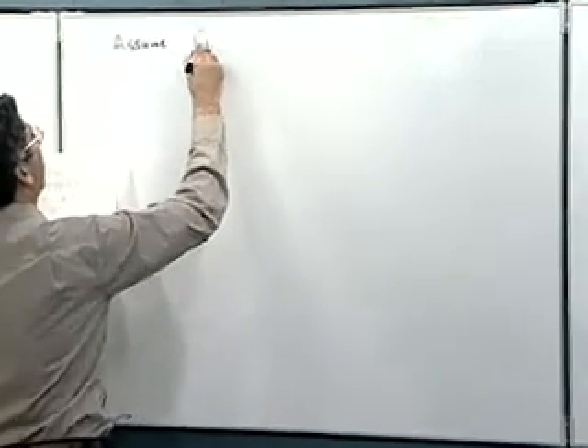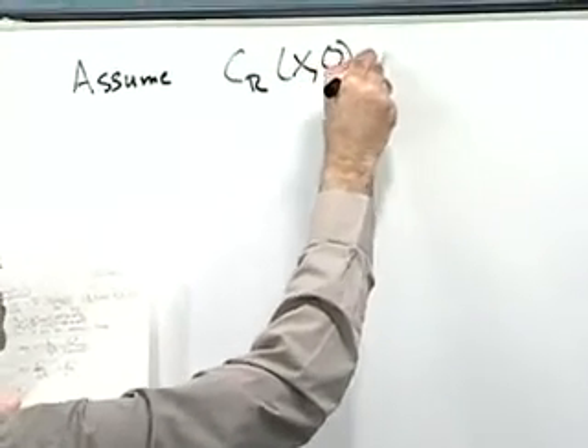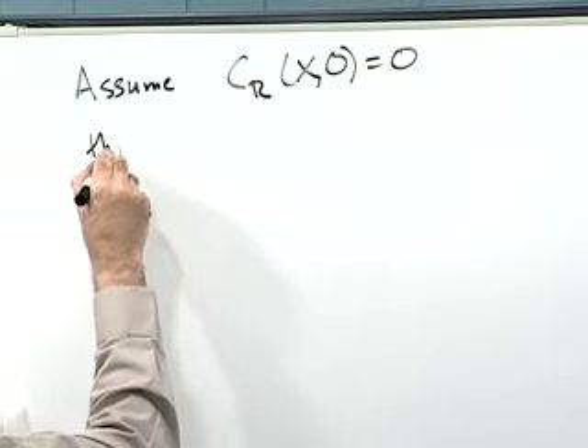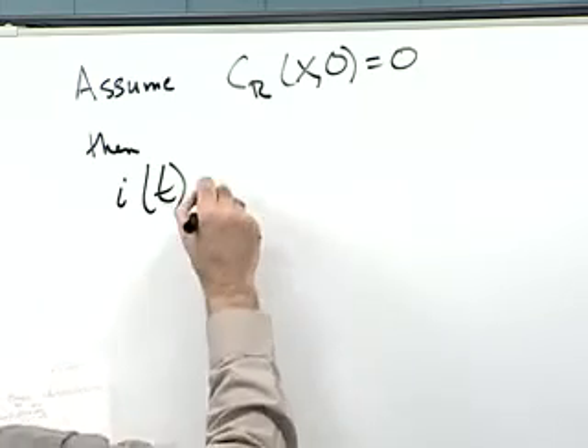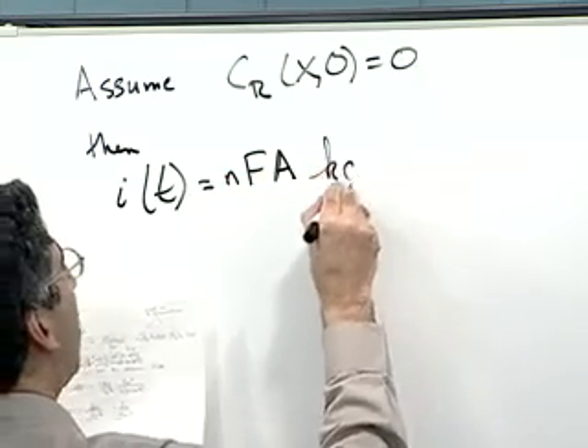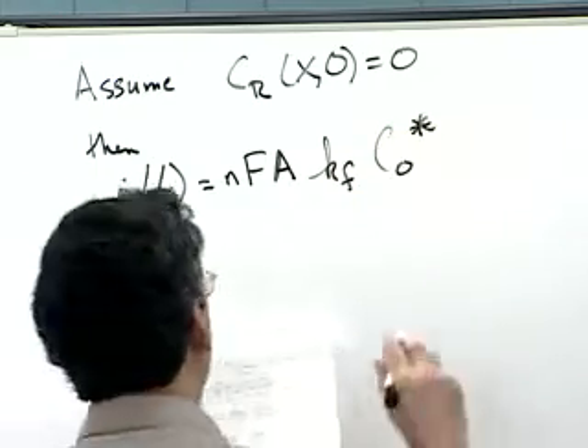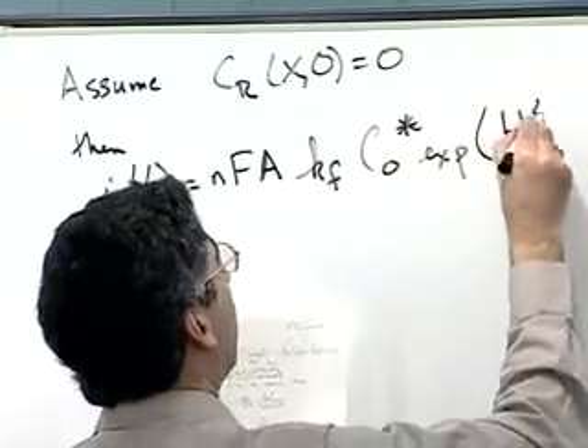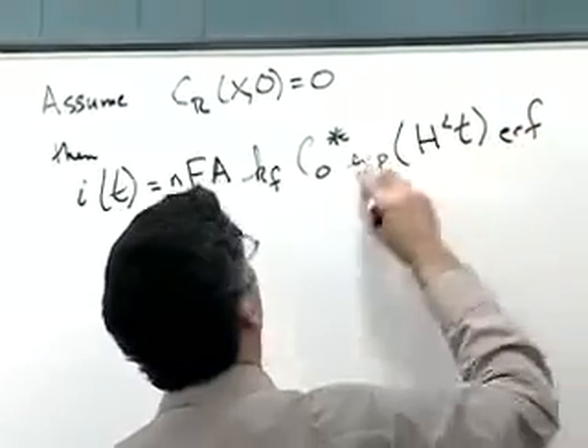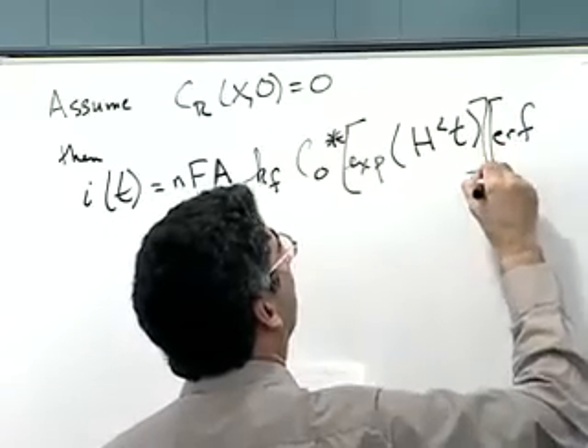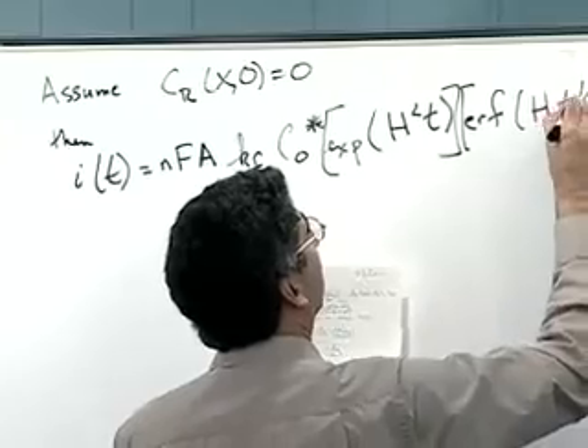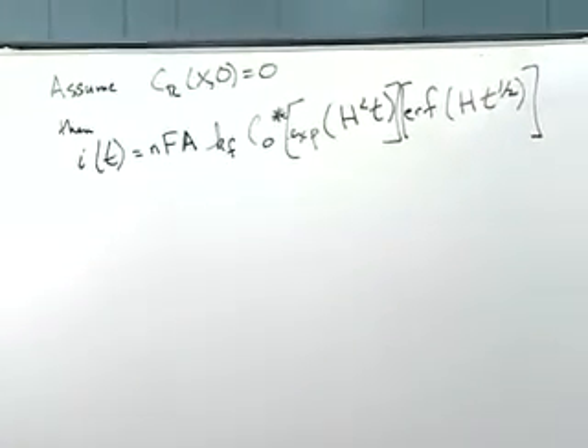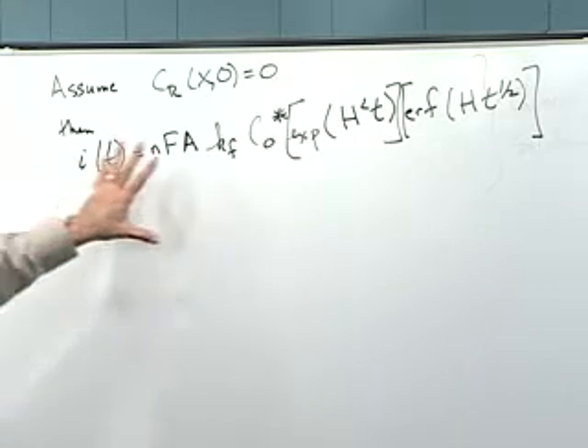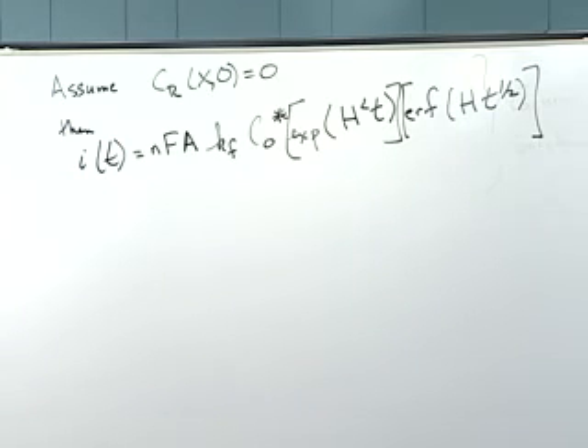And to make my life simple to start with, and yours, let's just assume that the reduced species at time 0 is non-existent. Then I'm going to come up with a statement that the current is equal to n, Faraday's constant, times the area, times the forward rate constant with its potential dependence, times the bulk concentration of oxidized species, exponential of h squared times time, multiplied by the error function of h t to the 1/2. Okay, so now you'll notice we have a different functional form here. It may not immediately pop out at you what that functional form is, but it certainly isn't a simple t to the minus 1/2 dependence associated with it.